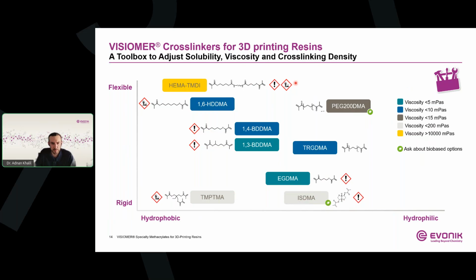One of the crosslinkers that maybe deserves special attention is the HEMA-TMDI. Unlike many traditional dimethacrylates, the HEMA-TMDI contains a relatively flexible linkage that combines the polymerizable methacrylate groups with urethane functions. And due to the effective hydrogen bonding of the urethane functionality, this promotes a good compatibility with urethane methacrylic or acrylic oligomers, which are among the most widely used oligomer classes in high performance SLA and DLP resins.